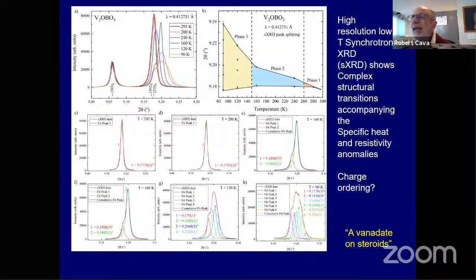Well, we used the best, highest resolution instrument we could find to do temperature dependent X-ray diffraction in a high resolution synchrotron at Argonne. And this is a comparison of the diffraction pattern. And here you see, first of all, how incredibly high resolution this machine is. One set of diffraction peaks doesn't change at all, but another set of diffraction peaks seems to split on cooling first into 2 parts and then into 4.